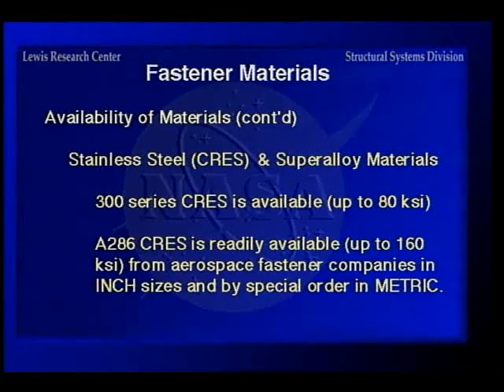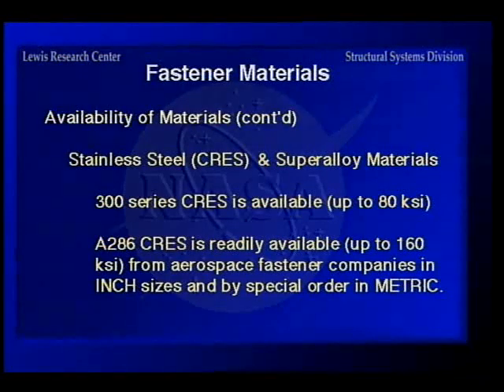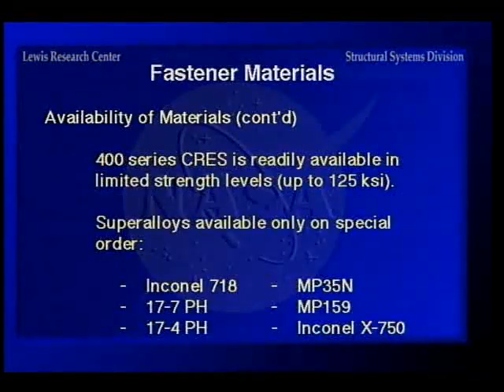Now, stainless steel, you'll see that designation for it, corrosion resisting steel, or CRES. Stainless steel is the same generic terminology, and the superalloy materials. Now, the 300 series that we're familiar with around here, you can get it up to about 80 KSI because it's not a heat treatable material, so the only way that you can get the strength up on it is by work hardening it in forming it, and that's about the strength that they get starting with annealed material. A286 we use all the time in the aerospace world, up to 160 KSI. It is a very common aerospace material, and you can get it in metric by special order in A286. The 400 series is available in limited strengths up to 125 KSI, and it's also available in metric, which I will show you further on.